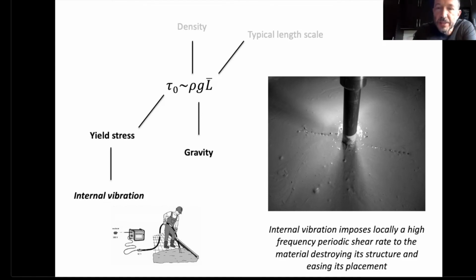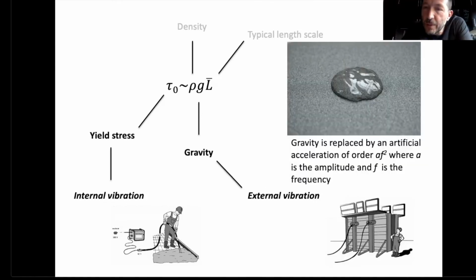The other possibility is external vibration. With external vibration, you don't touch the material really, but you replace the acceleration of gravity by an artificial external acceleration, where you have a dependency on the amplitude, which is often limited because we are trying to vibrate a very heavy, very big object, and on the frequency. Here we are speaking about things with amplitude around 1 millimeter and frequency around a few tens of hertz. But this often, in precast, allows for a perfect molding of the system when gravity is not enough to have a full molding and a full flow of the material inside the mold.